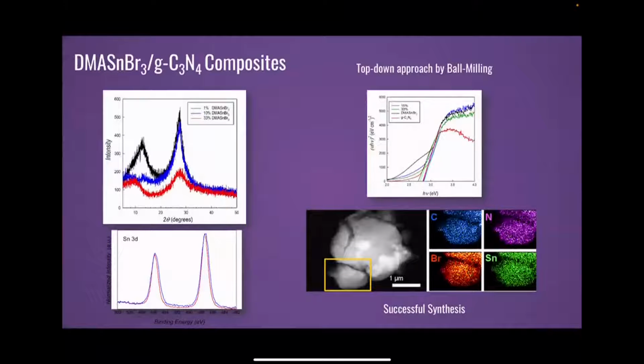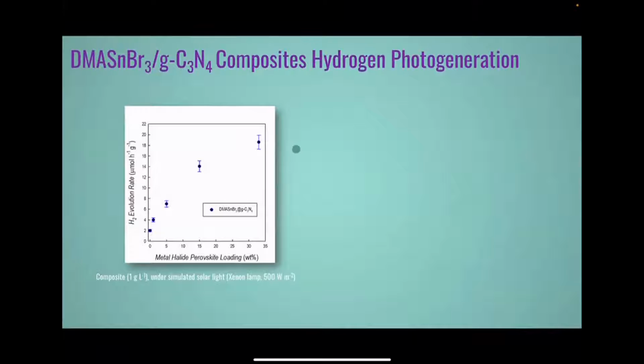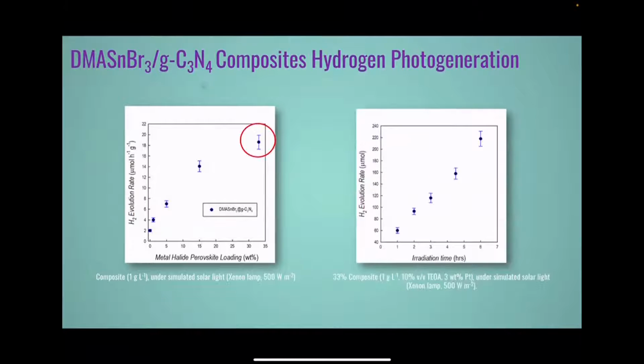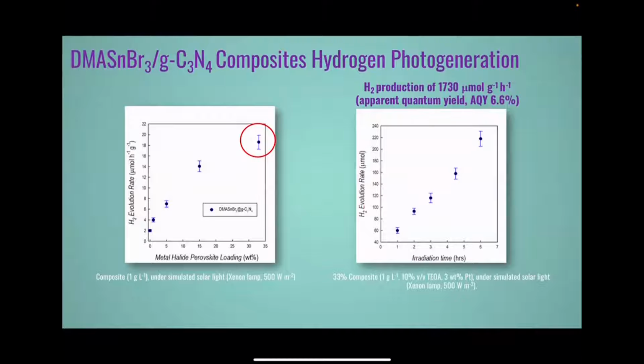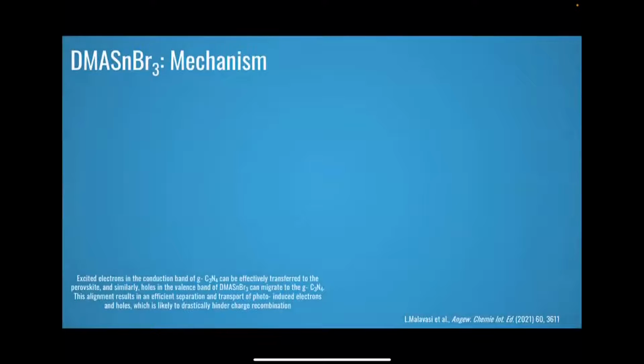And we create composites, okay? We skip the details on the synthesis, okay? And the main result was that we could improve the hydrogen evolution rate by improving the amount of metal perovskite loading with respect to the graphitic carbon nitride. And we could achieve something close to 2000 micromoles per gram-hour of hydrogen photogeneration by this kind of composite, okay? So this was a quite interesting and fascinating result, okay? It was the first one we achieved with our idea of using metal perovskites.